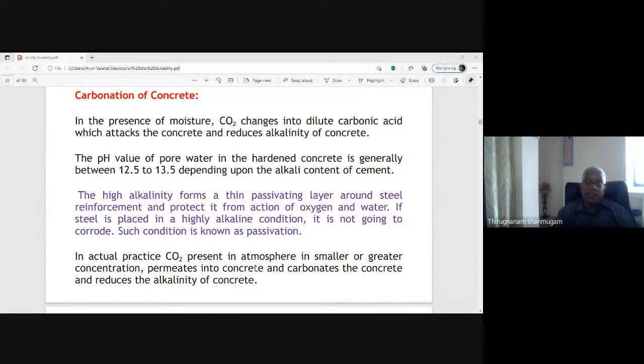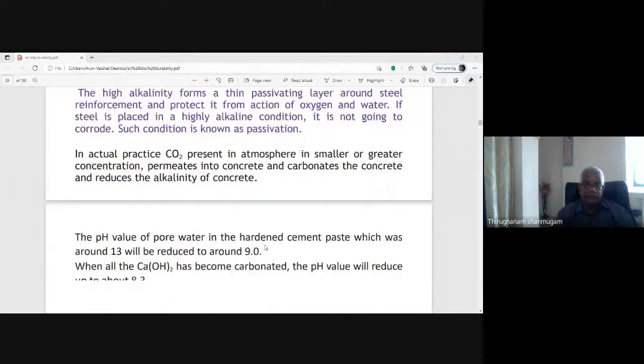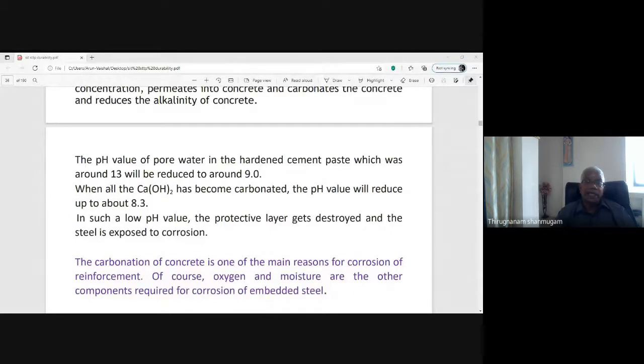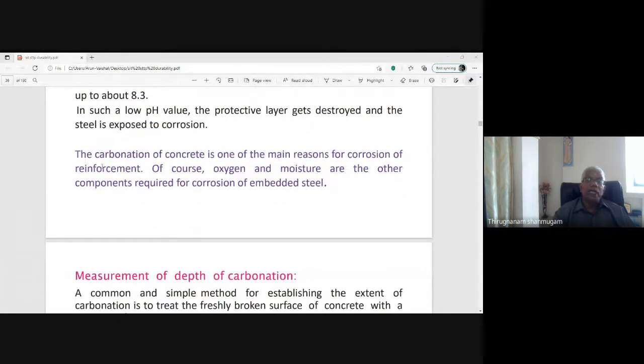In actual practice, carbon dioxide present in the atmosphere in smaller or greater concentration permeates into concrete, carbonates it and reduces its alkalinity. The pH value of the pore water in the hardened cement paste, which is around 13, will be reduced to around 9 by the ingress of carbonates. The calcium hydroxide liberated by the hydration of the cement reacts with carbonic acid, forming calcium carbonate. When all the calcium hydroxide has become carbonated, the pH value will reduce to about 8. At such a low pH value, the protective layer gets destroyed and the steel is exposed to corrosion. So carbonation of concrete is one of the main reasons for corrosion of reinforcement.